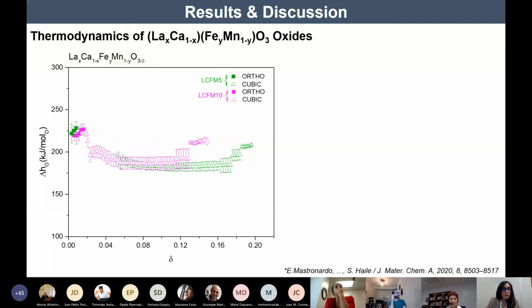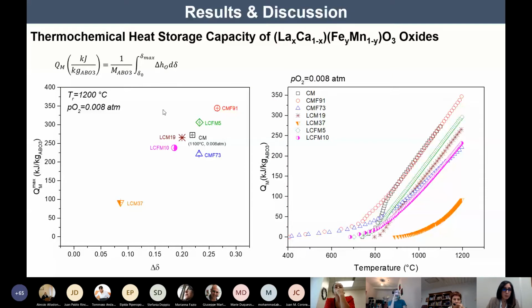If we look at the thermochemical storage capacity, evaluated under the most reducing conditions of 1200 degrees C and 0.008 atmospheres, we can see that CMF91 is the best candidate material, showing the largest storage capacity of around 350 kilojoule per kilogram. It is also able to store the heat in a wider temperature range with respect to the other candidates, while the 30% lanthanum doped composition shows the poorest one.